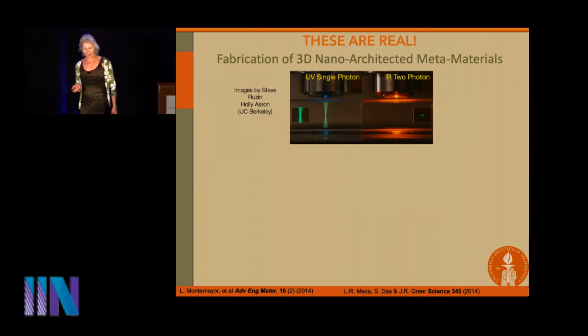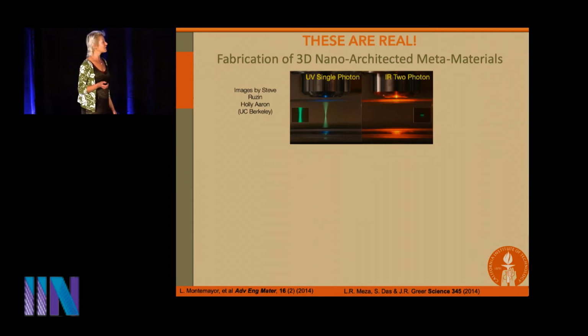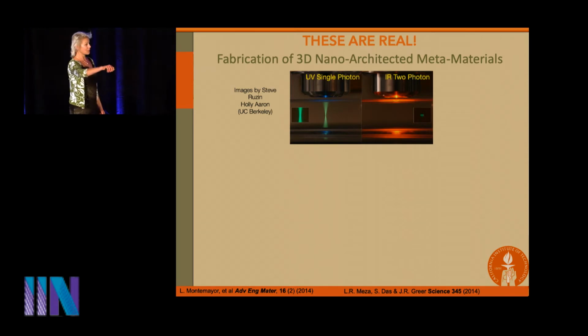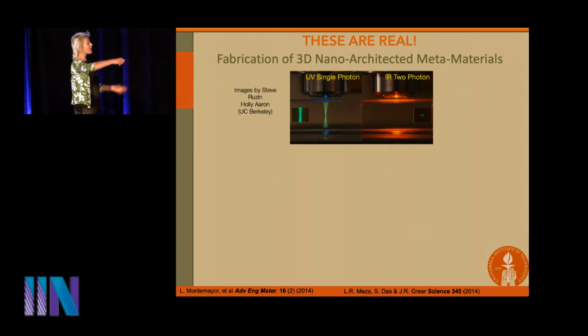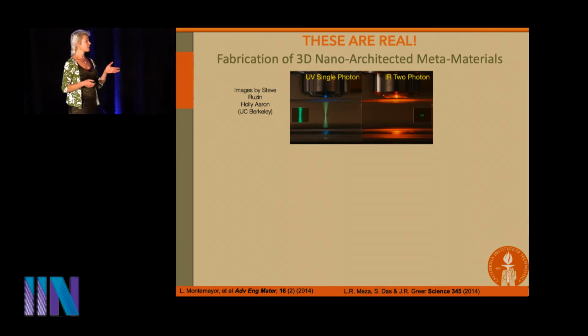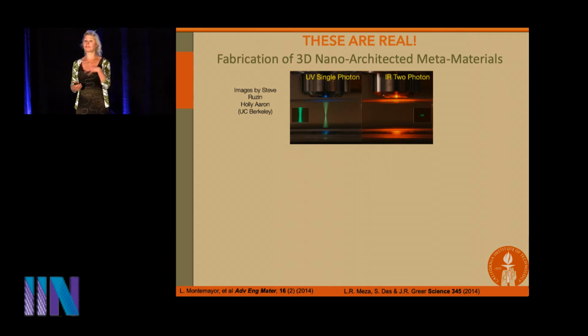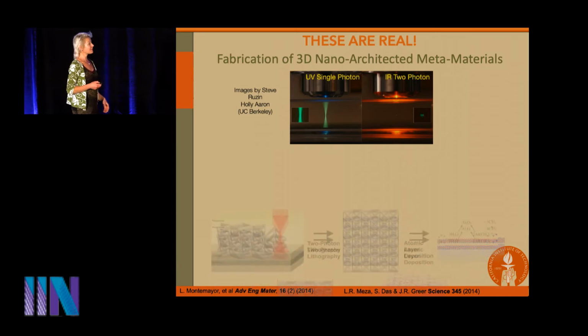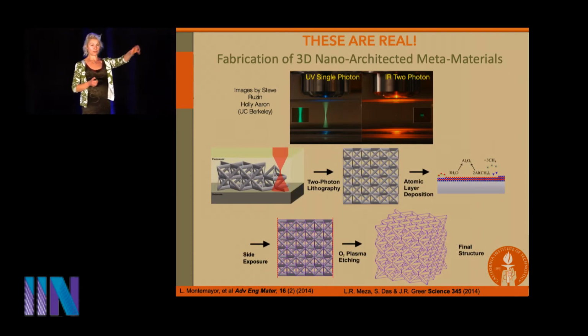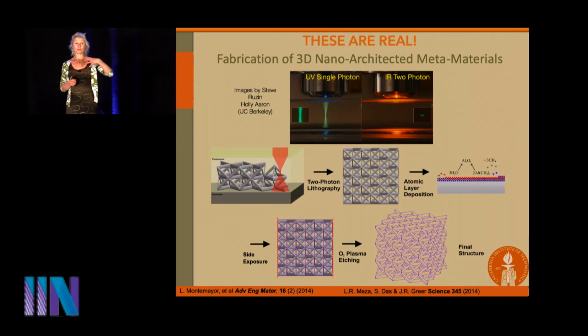So just a few words on how we create these very intricate geometries. Instead of using UV single photon lithography, which is a very typical process for two-dimensional lithography, two-dimensional architectures, we're using a process called two-photon lithography. And that allows us to concentrate all the light and all the exposure within the photosensitive resin in a single voxel. So it's the constructive interference of exactly two photons that gives rise to the sufficient amount of power to cross-link your polymer.